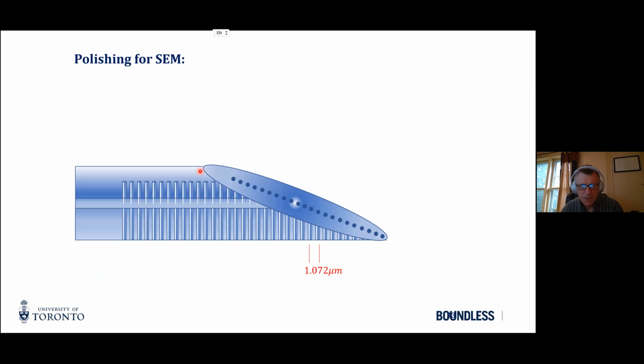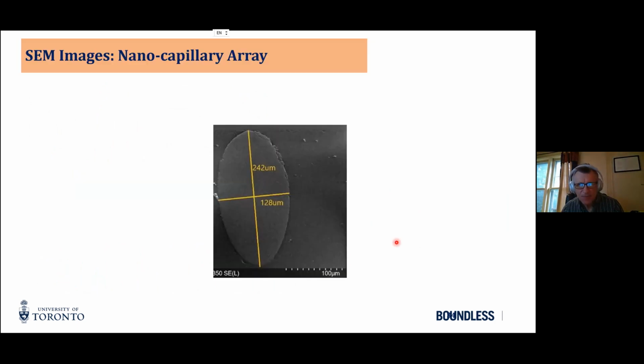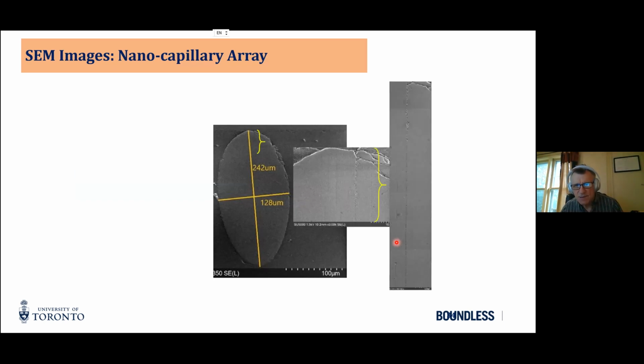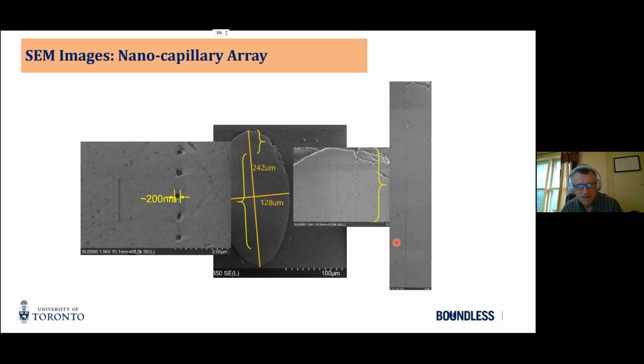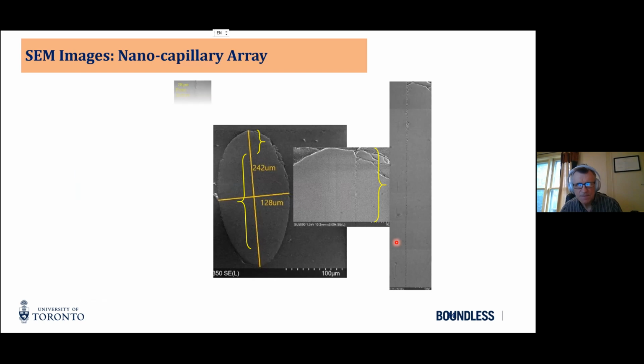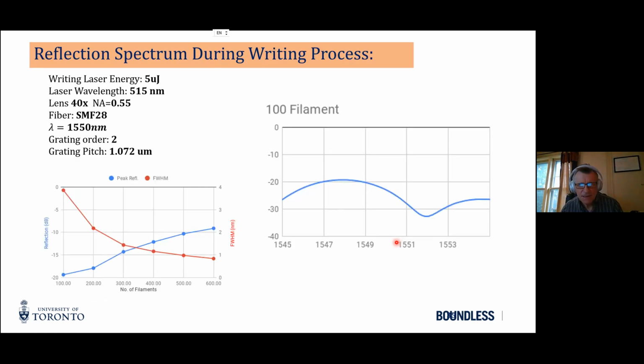So we make our nano hole capillary fiber Bragg grating. This is second order with 1 micron spacing in this case. And we're piercing the core and the cladding, so liquid should come in. If we cleave and polish this at an angle, here's the fiber under an SEM. And as you tune in closer and closer, you see that array of holes, and you infer that they're 200 nanometers in size. So we have characterized these fibers with the holes during writing.